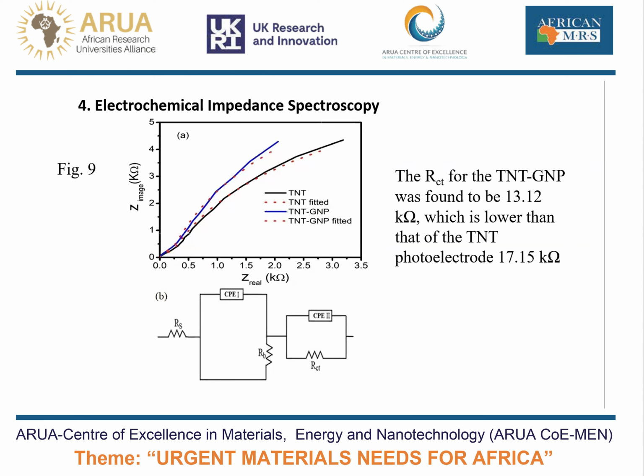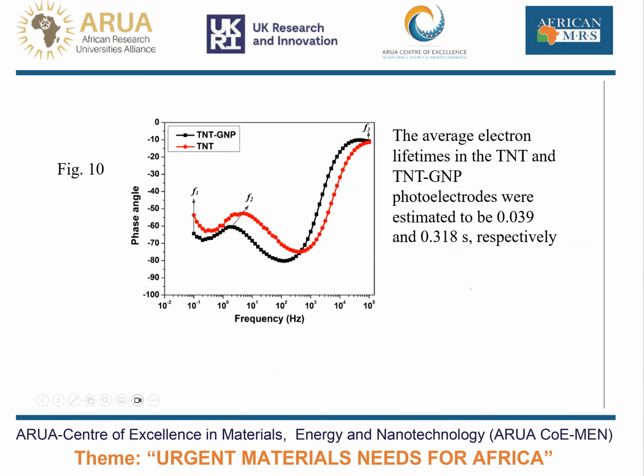In order to further understand the charge carrier transport and resistance or impedance in the system, we carried out electrochemical impedance measurement. And in order to understand the charge carrier transport resistance, we simulated a circuit, which is shown in figure 9B. And we discovered that the charge transfer resistance for the decorated film was low, which is about 13.12 kilo ohms compared to that of the bare titanium oxide, which shows why the decorated film produces higher photocurrent density as compared to the bare film.